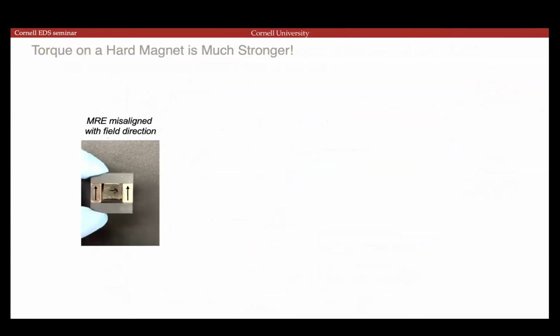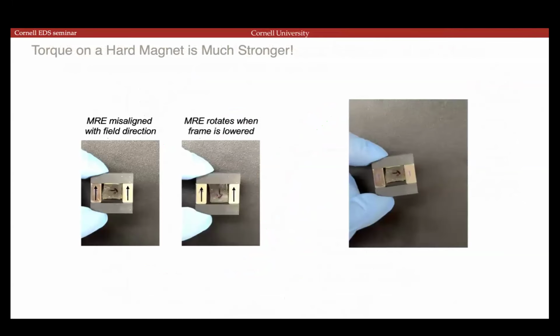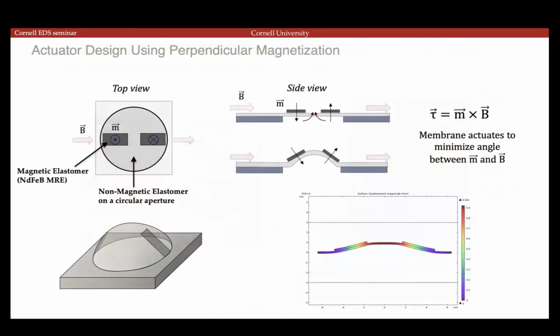But you can see here that the difference is going to be quite strong. So if we start with a material on a table that is completely misaligned with the magnetic field, just when it experiences the magnetic field, it'll completely rotate 90 degrees despite all of the friction that's present. So we formed magnetic haptic taxels, tactile pixels, of these with the magnetization either oriented up or down. If they are oppositely oriented and you apply an in-plane magnetic field, they'll each torque towards the field and bend the film upward.